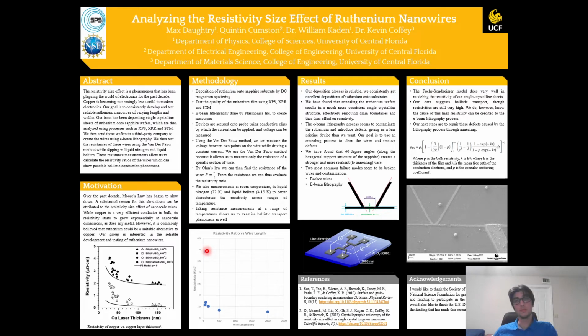So to go into the results of this whole process, it seems that our deposition process is very reliable, and we consistently get excellent depositions of ruthenium. And we found that annealing the ruthenium wafers results in a much more consistent single crystalline structure. The annealing process effectively reduces or eliminates any grain boundaries between the crystalline structures, which greatly reduces resistivity.